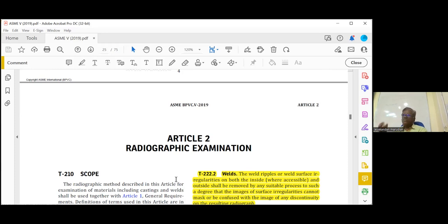Coming to MT, there is no temperature specified in the code. You have to follow the particle manufacturer's recommendation. Particle means the liquid or magnetic particle chemical. Only that recommendation you have to follow. Again, if you want to go outside the recommendation, you have to qualify the procedure at that temperature. Now coming to RT, again there is no temperature specified in the code for taking a radiograph. So as long as you can protect your cassette from the heat, you can take a radiograph. There is no temperature, but for film processing, there is a temperature given in API 577. Film should be processed at 68 degrees Fahrenheit.